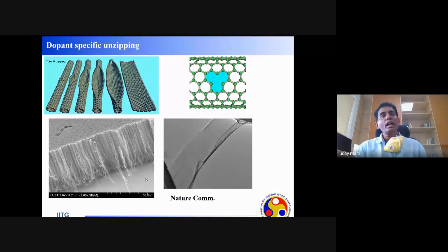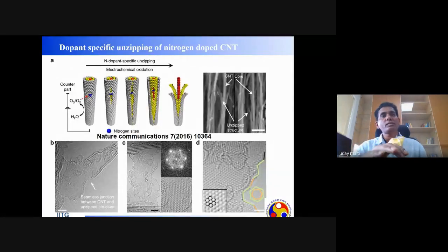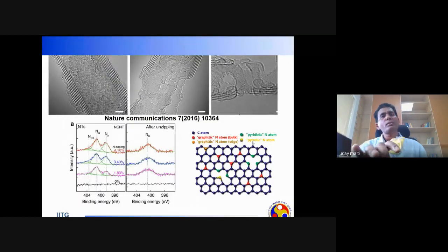Okay. So here we did some dopant specific unzipping. This is a carbon nanotube. When it is unzipped, it gives rise to nanoribbons of graphene, and this is the specific process by which we have done it so that it remains crystalline in nature. So it is very different from the other reported methods where there is a lot of disorder. You can see the crystallinity from the TEM image. From this atomic resolution image, we have also confirmed that crystallinity is there.